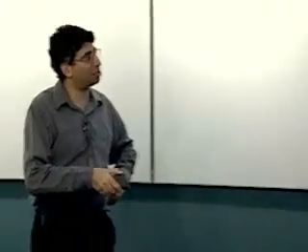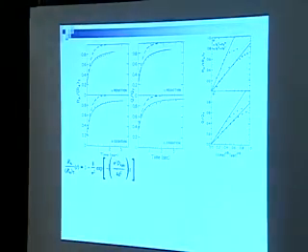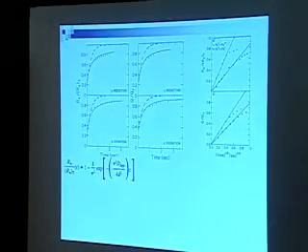And so he comes along and comes up with a new equation. That is, he does the normal thing, takes Fick's second law, changes the boundary conditions so they are finite diffusion boundary conditions, does the Laplace transform, and comes up with this equation. He actually did it in terms of current; we integrated it to get charge, and then I changed it to be in terms of reflectivity here.